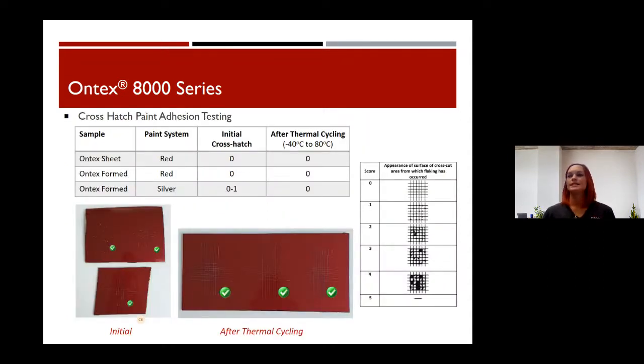We did do some testing. We had some testing done with some outside suppliers just to make sure it was passing muster. One of the automotive grade tests for paint adhesion is this crosshatch test. We looked at red, we looked at a silver, and you can see even after thermal cycling fully from -40 to 80 C, performed very, very well. So we got good adhesion on the paint.